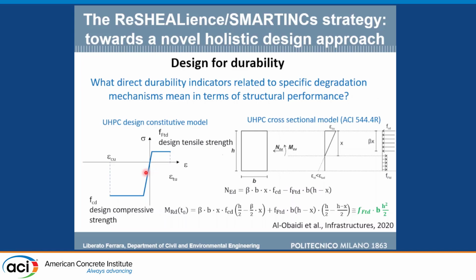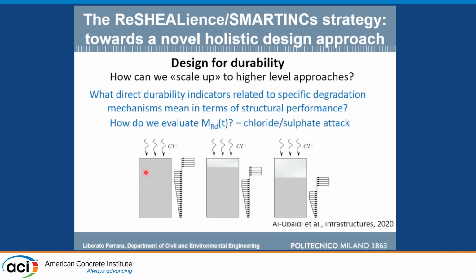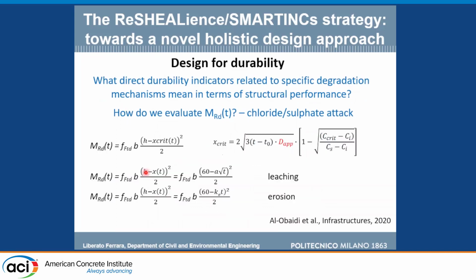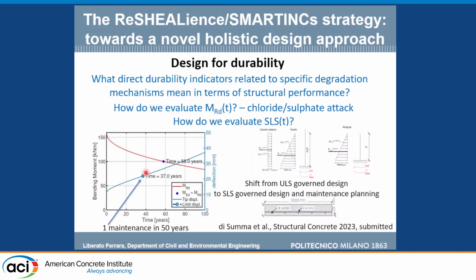So you basically compute moment equilibrium with a stress block in compression and a stress block in tension. And what we did, we reduced the cross-section as the attack progressed. A very severe assumption in this case, but we said, let's start with that. So we embedded into the moment equations Fick's law or other degradation laws.